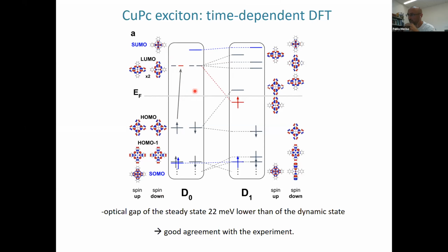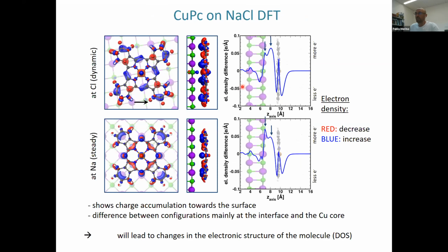But the important part here is that we simulated the lattice by a net of ions, and we saw that there is a 22 millielectron volt difference in the exciton energy between the steady and the dynamic states, which is in good agreement with the experiment. And this is because we are having some charge reorganization in the interface, and actually here we see in red and blue the decrease and increase of electron density.